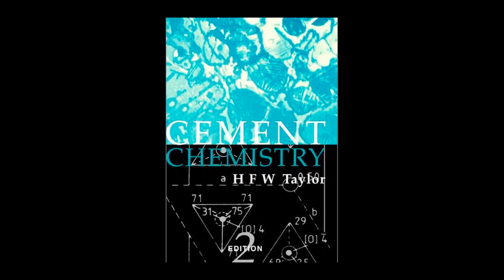Okay, next up, pulverized fuel ash, or fly ash, PFA. Fly ash is a byproduct of coal combustion, and it's typically composed of these spherical, glassy particles. Class F fly ash, which is low in calcium, acts as a traditional pozzolan, reacting slowly with CH over time. Its fine spherical shape is beneficial in two ways. It improves workability, and the particles act as powerful nucleation sites. What does that mean? It means they actually accelerate the reaction of alite in the middle stages of hydration by providing these ready-made surfaces for CSH to precipitate onto.